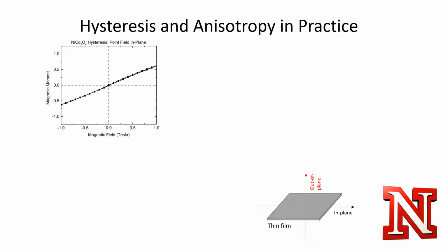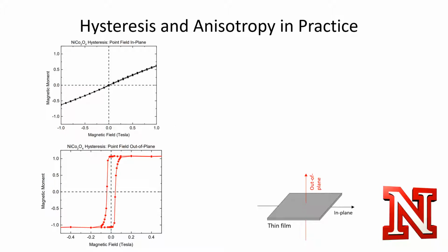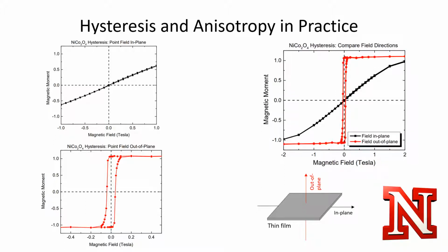The in-plane axis shows very minimal coercivity and remanence. The out-of-plane axis could not be more different. The remanence is nearly as large as the saturation magnetization, and the coercivity is nearly as large as the field required to saturate the magnet. Comparing the two graphs on the same scale clearly shows that the in-plane axis is much more difficult to magnetize, necessitating far stronger fields to get to the same magnetic moments. Because of the discrepancy with shape anisotropy, we know that nickel cobalt oxide must have a different form of anisotropy giving it this behavior, such as the anisotropy arising from crystal structure.